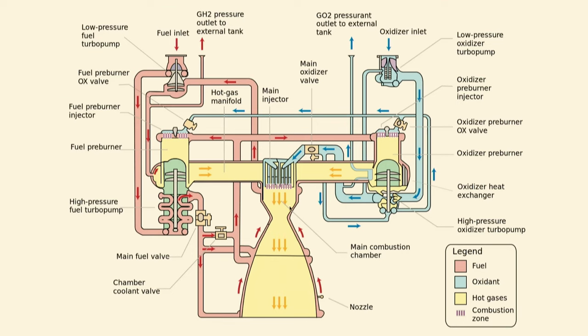You have to pass them through at tremendously high pressure, because it has to be injected at a higher pressure than the combustion chamber pressure, which could be maybe 50 atmospheres, 100 atmospheres. So it has to be injected in at an even higher pressure to be injected in the first place. And also, because the temperatures on the combustion chamber walls are so high, most things would boil straight away. So you have to pressurize them a great deal in order to get the boiling temperature up, and therefore make them able to absorb enough heat from the combustion chamber.